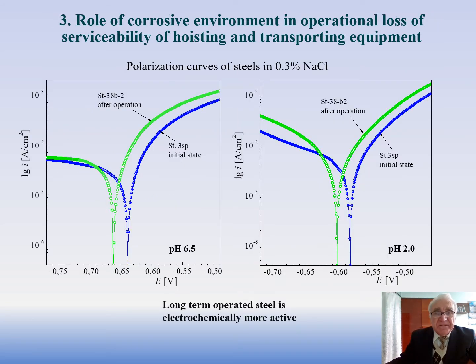Role of corrosion environment in operational loss of serviceability of hoisting and transporting equipment. One of the consequences of the operational degradation of port metal structures is the intensification of corrosion process confirmed by electrochemical studies. The long-term operated steel corrodes faster than as-received or normalized one. This means that the current technical state of a metal under operation should be also taken into account when predicting corrosion losses and metal thinning.